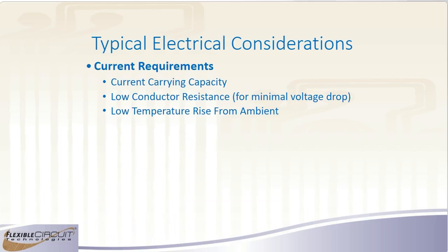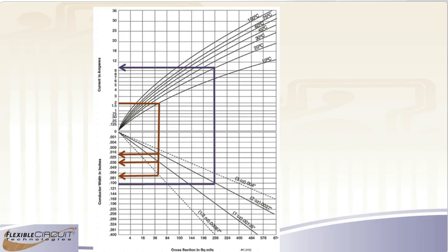So if you look at your current requirements, anytime you have more than a couple hundred milliamps, you have to look at the trace that's going to be carrying that current. There's enough other things in your system typically that are producing heat, and so you don't want the flex circuit to be a heater in and of itself. So you're looking to keep your resistance in your traces to a minimum, and that will reduce the amount of temperature rise that you have. And this is a snapshot from IPC 2152 that shows how you can get more temperature or less temperature in your traces based on the size, the thickness, and the width of the circuits.